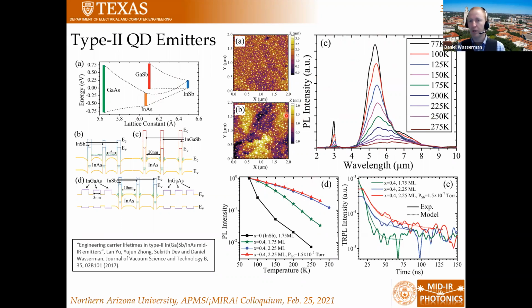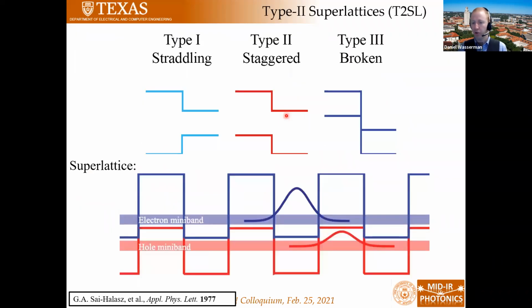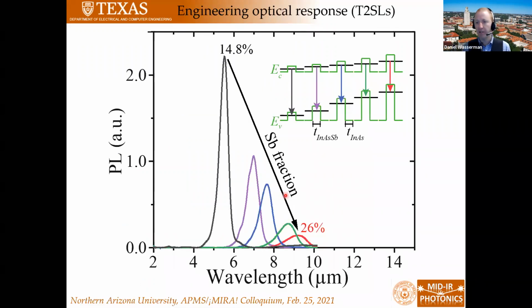So we can use these type 2 quantum dots, for instance, for mid-IR sources, but we can also make superlattices. So we can stack together these type 2 materials, so hundreds of layers of these, and instead of forming discrete states, what we get are mini bands. It's a superlattice. We're essentially forming a semiconductor on top of another semiconductor band structure, or two other semiconductor band structures, right? And by controlling the geometry and the materials, you can essentially control the energy spacing between your electron and your hole mini bands. What this means is that by designing different combinations of materials, or thicknesses of materials, we can actually cover everything from 5 out to 9, or even out to 15 microns now, if we want to, and essentially build our own semiconductors, quantum engineer our own semiconductors for operation in the mid-infrared and across the mid-infrared.